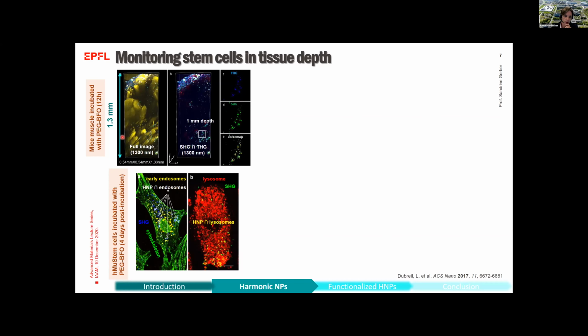Here you have the full image with excitation at 1300 nanometers, where you can see the nanoparticles, which in some areas of the tissue form small aggregates. What's interesting is that to get better resolution and distinction of those nanoparticles, it's possible to apply the colocalization protocols we discussed before. Here you can see the nanoparticles are clearly present up to more than 1 millimeter depth in the tissue.